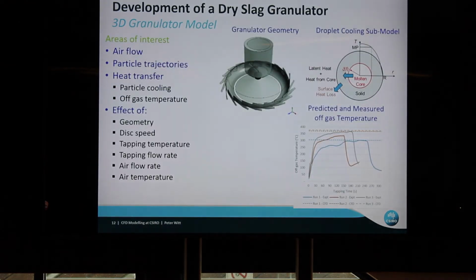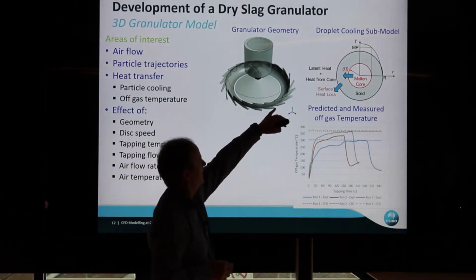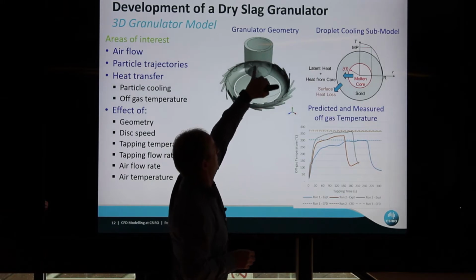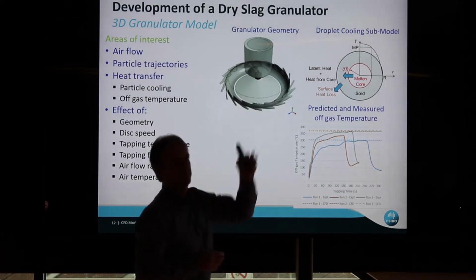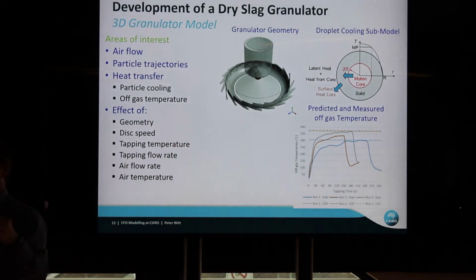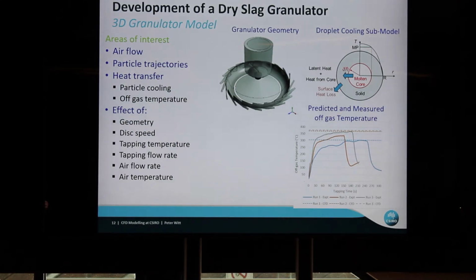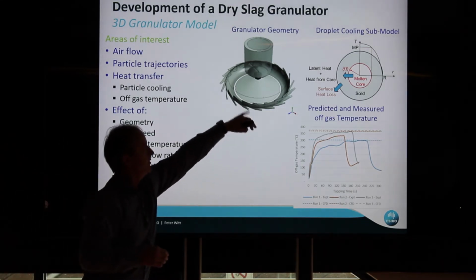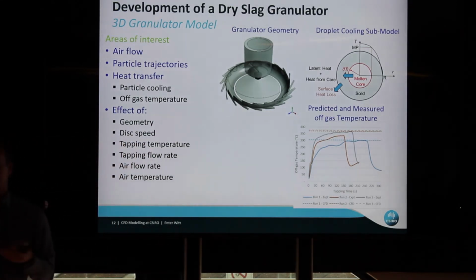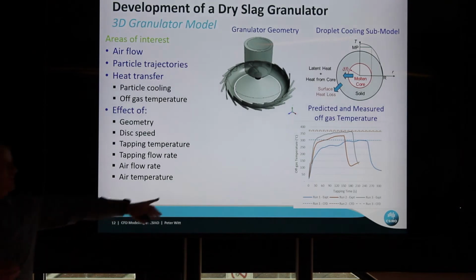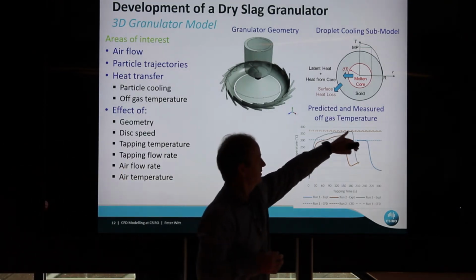Then on the granulator, we did a lot of work simulating the granulator where we have air coming in, spinning around, going out through the top, the particles coming off the disc. So we use the disc model to get an idea of the temperature and the size of the droplets coming off the disc. Then we track those through the granulator, look at how they cool, and look at how they travel through the granulator and then go out through the bottom. And from that, we can get an idea of what the off-gas temperature would be under different conditions.